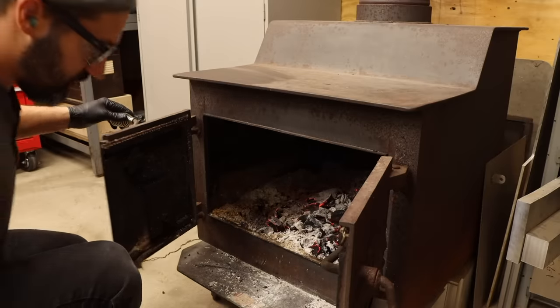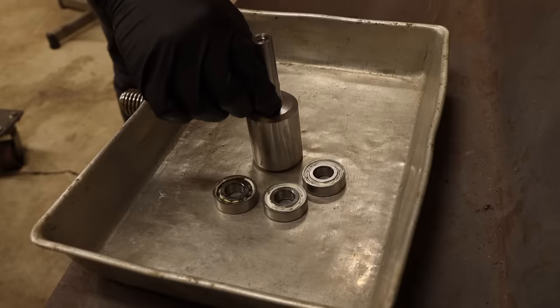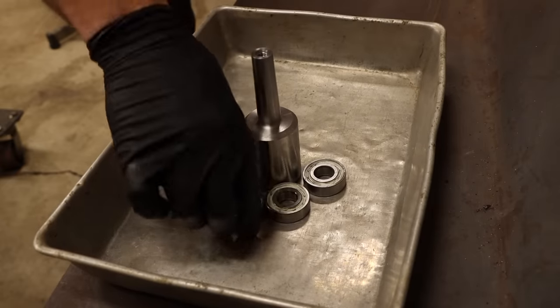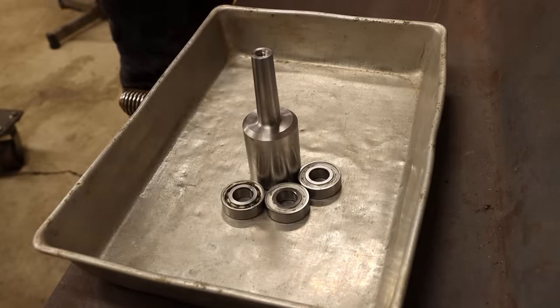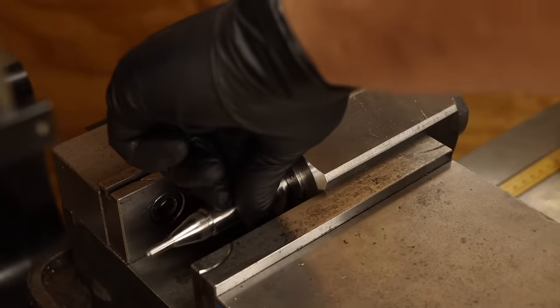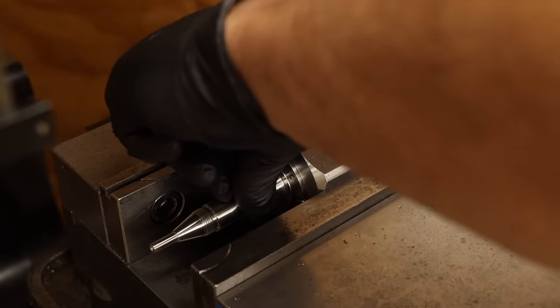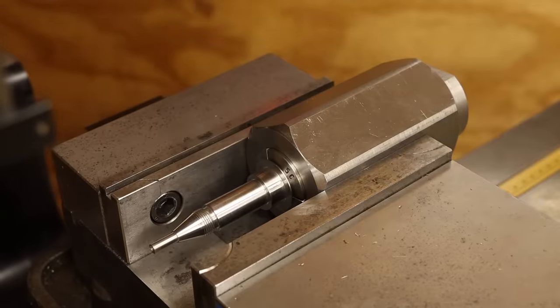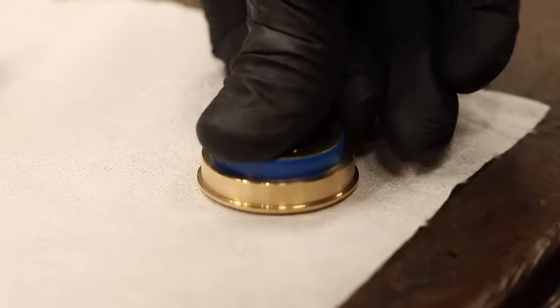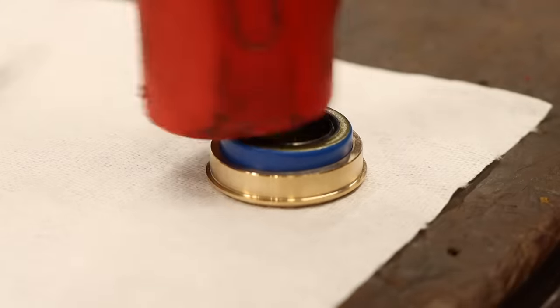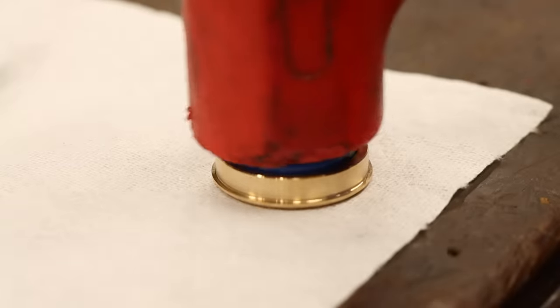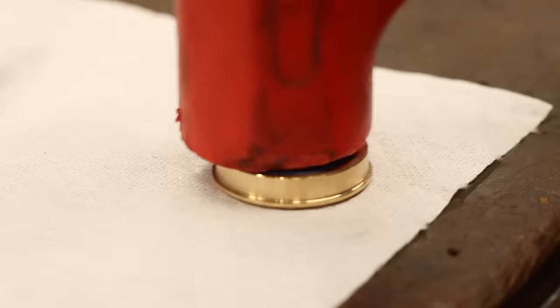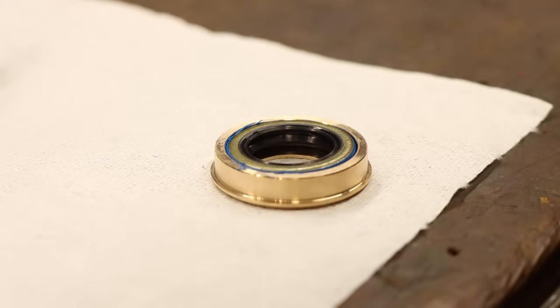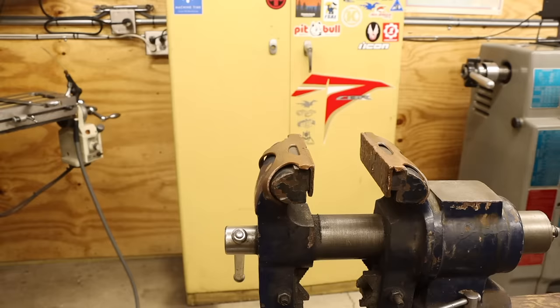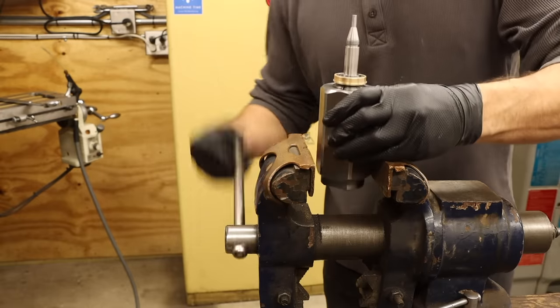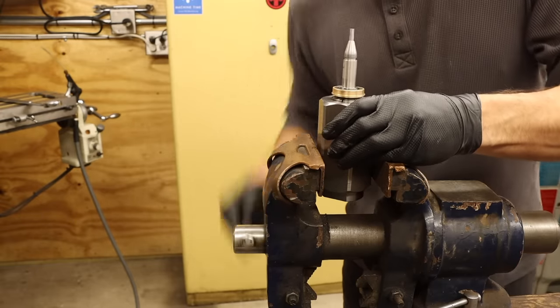Warming the bearings up should expand them slightly, helping with assembly, so I'll set these over on the wood stove, and I'll do the same for the body. In the meantime, I'll get the spindle mounted in a collet block, and then put this in the freezer to shrink it a bit. The seal just presses into the bronze sleeve. Now that things are sufficiently warmed and cooled, everything should just slide together.